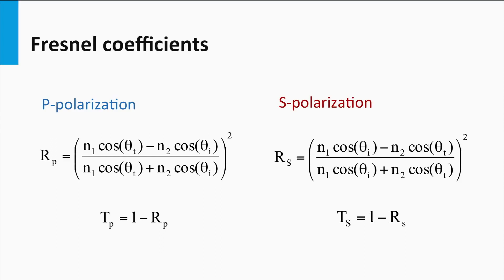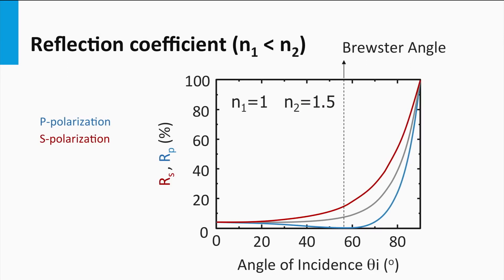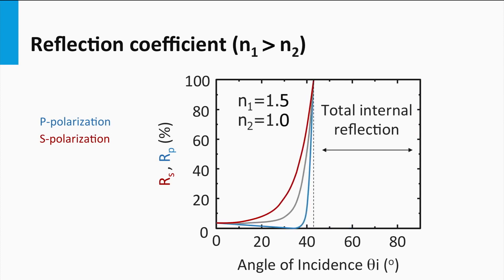For light at perpendicular incidence, that is an angle of incidence of zero degrees, the reflection and transmission are equal for both polarizations. In this graph you see the relation between the reflection coefficient for s- and p-polarized light, when medium 1 has a refractive index of 1 (air) and medium 2 has a refractive index of 1.5 (glass). The p-polarized light has an angle at which reflection is zero — this is called the Brewster angle. The gray line represents the average for randomly polarized light. If light goes from a higher to a lower refractive index, reflection becomes 100% above a certain angle — this is total internal reflection, occurring above the critical angle, which can be calculated using Snell's law.